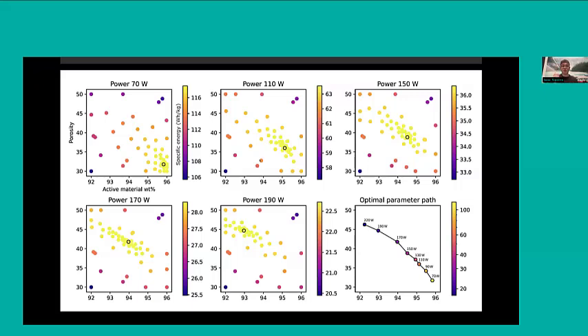So you can see here that in the top left, we've got the low power situation. In the low power situation, the simulation tells us that what we want is a high active material weight percent. So this means we want to pack the electrode full of the active material, in this case NMC, and that means that we'll get a higher energy density because we have more of this active material. And we also want a low porosity. So this means kind of calendar it more and don't have as many gaps in the porous structure, because at low power, we're not driving the cell very hard. There's not a lot of current. And so what we're doing there is we're not rate limited by diffusion.